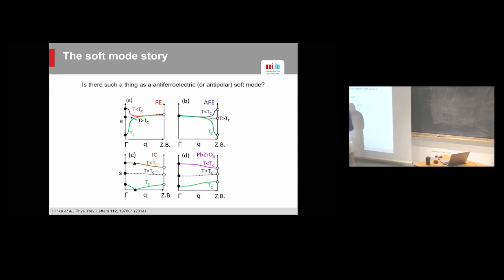This is what happens for incommensurate modulation. In that case, the mode that goes to 0 is neither at gamma nor at the zone boundary, but somewhere in between at some incommensurate position, and this leads to incommensurate phases. And finally, and this is the scenario that they discuss in this paper, for classical anti-ferroelectrics like zirconates, what happens is rather that the whole branch is shifting up and down, okay? But you don't really have that.